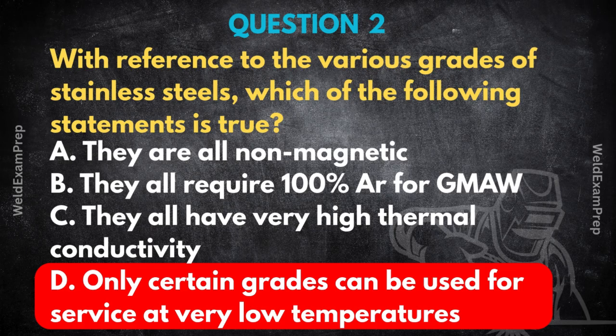However, and this is the key part of option D, not all stainless steels are suitable. Oh, okay. Those ferritic and martensitic grades we mentioned earlier can suffer from severe embrittlement at low temperatures. They become like glass, so they'd be completely unsuitable, even dangerous for those applications. So it really comes down to the specific grade. Absolutely. You have to know the grade and its specific metallurgical behavior, especially regarding temperature.